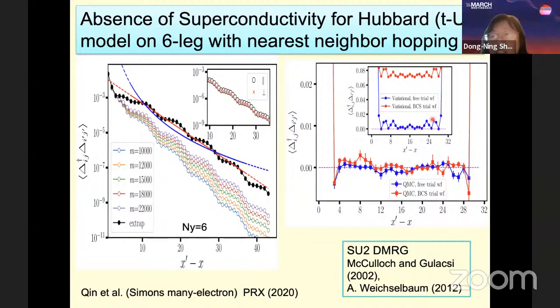For the square lattice, as long as you consider a large U model or t-J model, if superconductivity is obtained in some parameter region, the symmetry is indeed d-wave. That's maybe intrinsically related to the very strong repulsion in such systems. So you want to say that the strong Hubbard interaction is almost guaranteeing you the d-wave symmetry? Yes, for most of the recent simulations, d-wave. Why is that? Is there a simple way to see that?